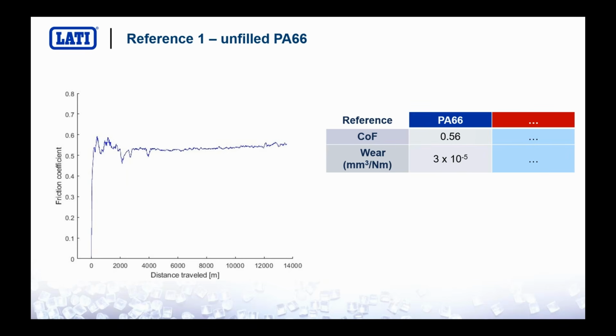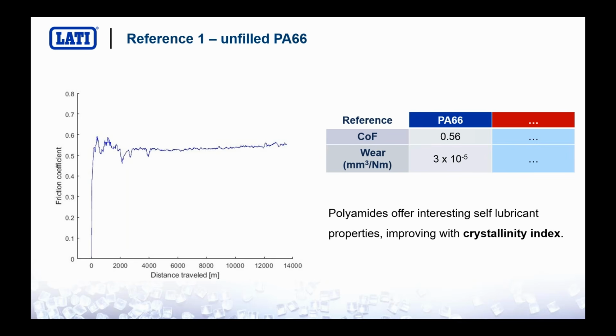What is possible to achieve from this plot is for sure the friction coefficient, which for polyamide 66 is more or less 0.56. And it's possible also, with the device that we used, to detect the wear resistance expressed in cubic millimeters over Newton per meter. And as you can see, after a first peak, the value of the friction coefficient of polyamide 66 tends to a plateau.